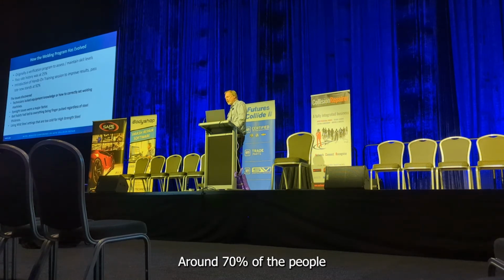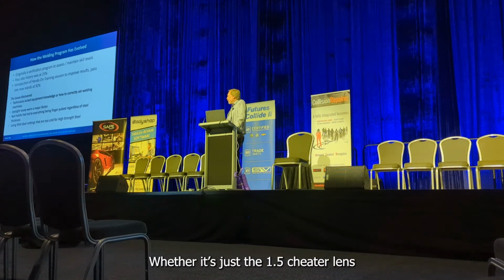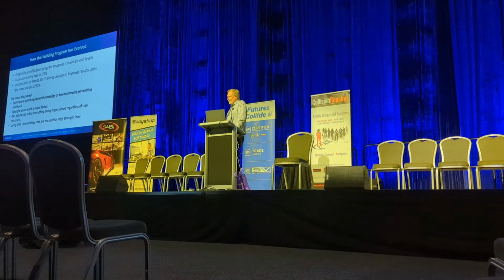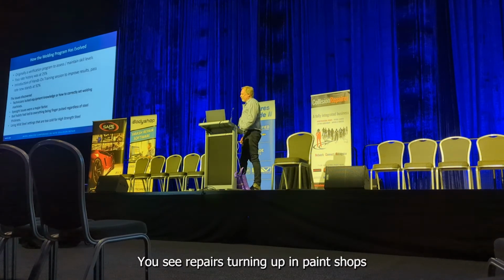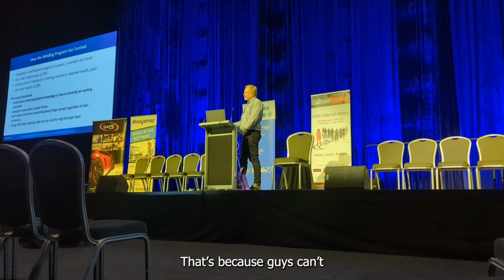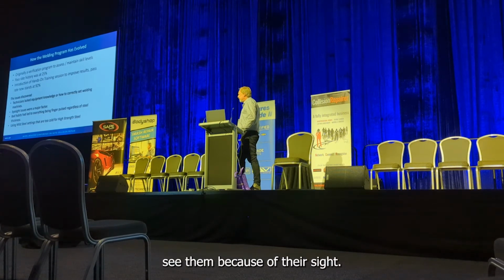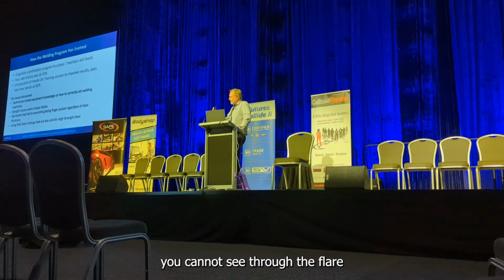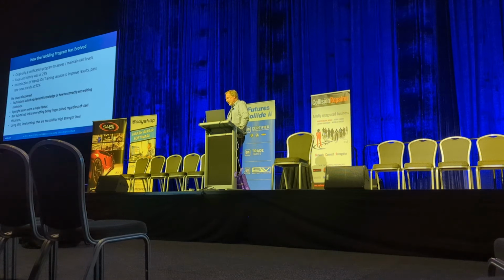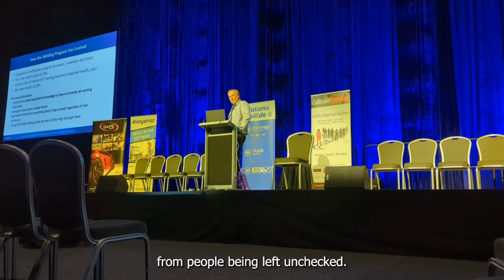Around 70% of the people that turn up to these welding programs, we have to actually put magnification lenses into their helmets, whether it's just a 1.5 cheater lens or even up to a +3 magnification. So those guys need to go straight down to the optometrist and get their eyes checked. You see repairs turning up in paint shops full of pinholes. That's because guys can't see them because of their sight. If you have sight issues with welding, you cannot see through the flare, so you can't actually see what's happening to the puddle.